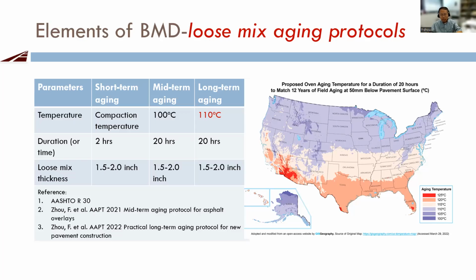Why we choose 20 hours? Because 20 hours, we think, corresponds to the binder PV aging of 20 hours, which has been used for 3 or 4 decades. That means it's practical enough, people have been using it, not changed yet. And it also gives people flexibility to work within the working hours window. So that's how we choose 20 hours.